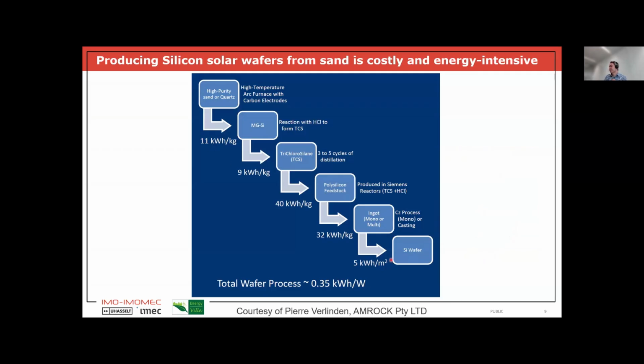This shows you the steps that you need to undergo to come from sand, high purity sand or quartz, to the silicon wafer. And for each step, it's also estimated how much energy you need per kilogram or per square meter to produce that step. And so we have a lot of high energy intensive steps, a lot of high temperature steps are needed. So first, you need to go to very high temperatures in the furnace to make the sand into metallurgical grade silicon. The metallurgical grade silicon is already relatively pure silicon, but not pure enough. So we have to further purify it.